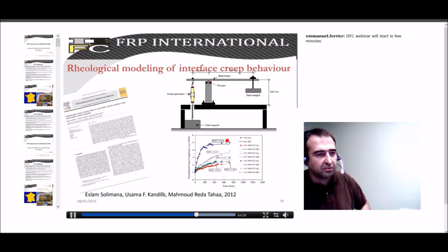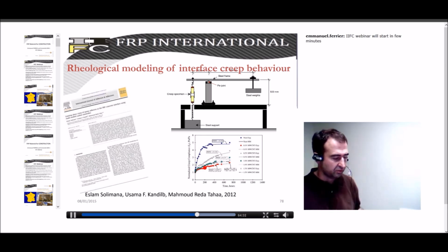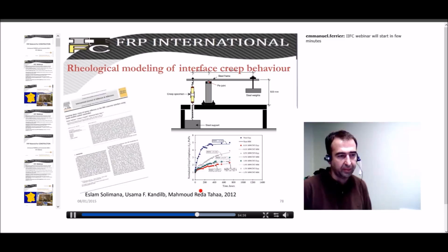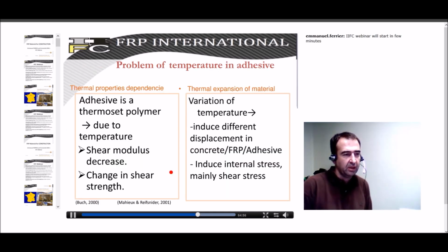What is interesting is that the modeling has been done as I have done, and that they have also proposed to try to improve the creeping behavior using nano carbon particles that can be used in several kinds of polymer used in the field of aeronautics. And these authors conclude that it can be very interesting to use some new polymer to limit the problem of creep in this adhesive. So this paper can be very interesting also, and it is quite a new paper.